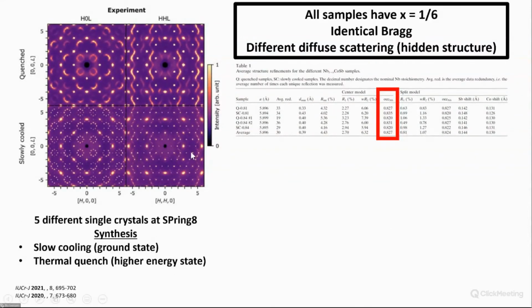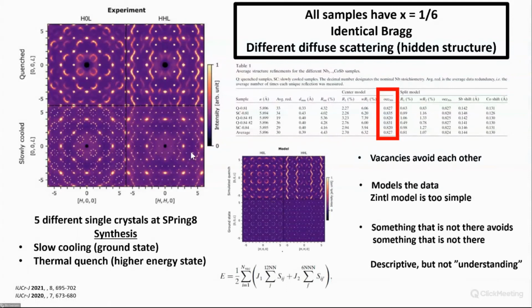So what's going on? And then Nikolai, the brilliant student I had, said, okay, what if the vacancies want to avoid each other? So there's a penalty if I put vacancies next to each other or as next nearest neighbors. In fact, you can make a fully ordered structure where you never have vacancies as nearest neighbor or next nearest neighbor. So we can make some kind of energy function, saying if this is 0, then I have no next nearest or nearest neighbors, but otherwise we have this penalty. And then you can start doing a simulation of different structures. And when you do this, you can exactly reproduce the diffuse scattering that we measure in the different crystals.